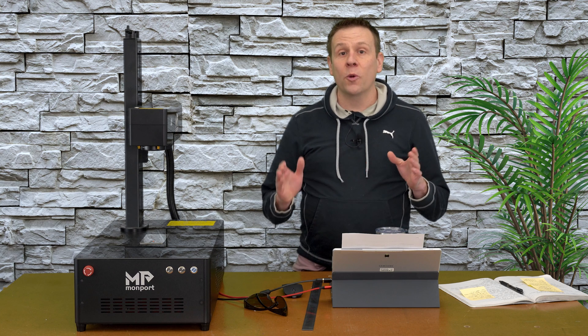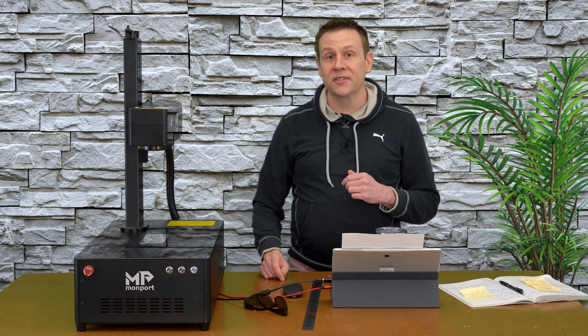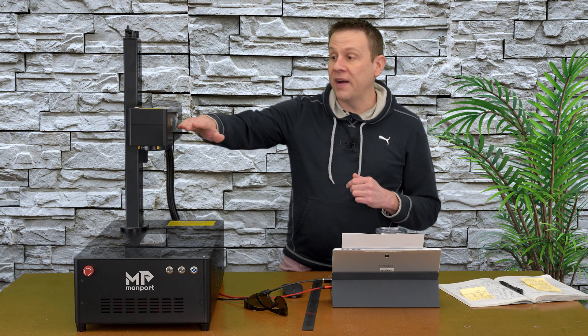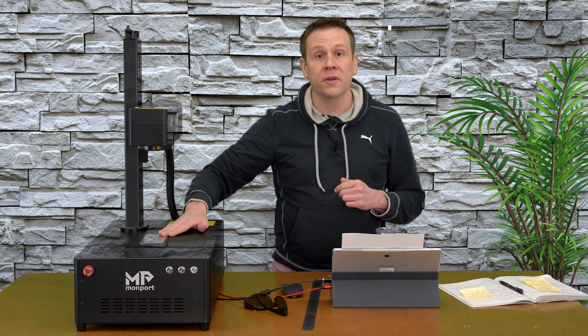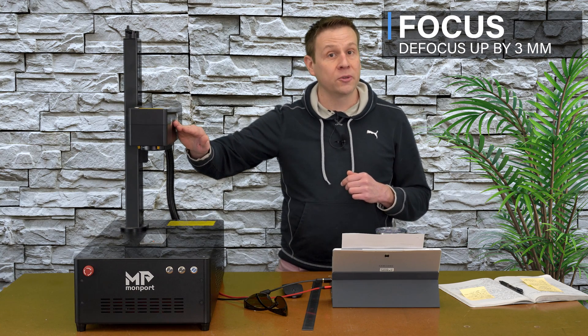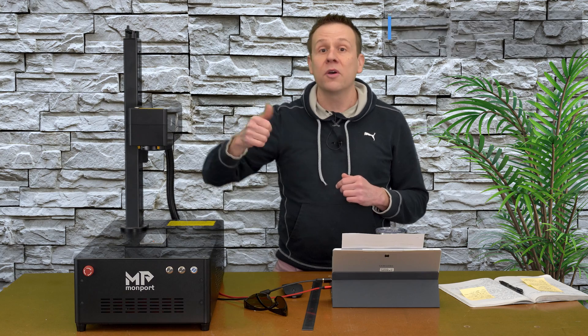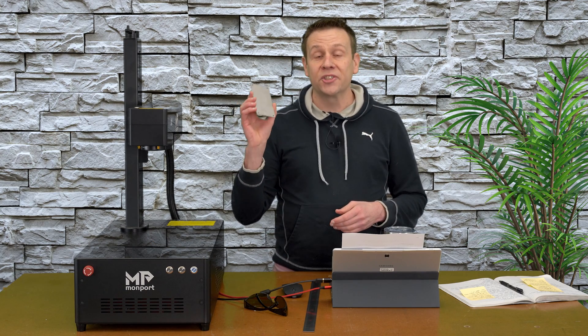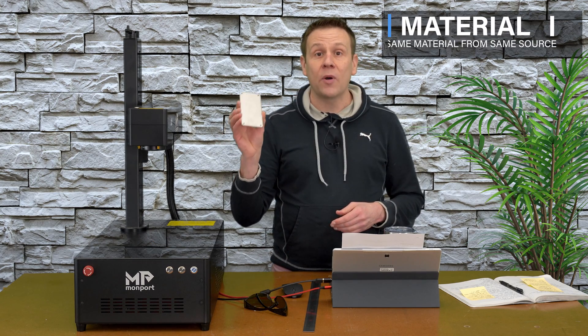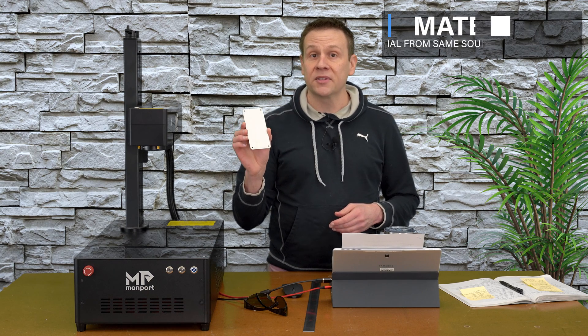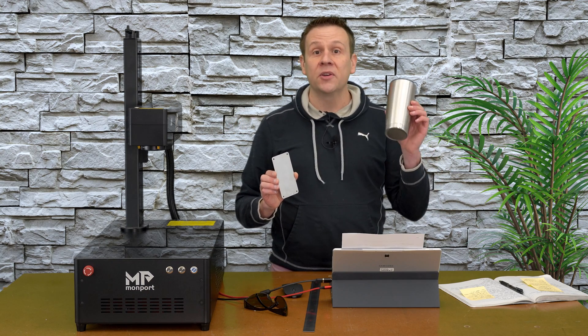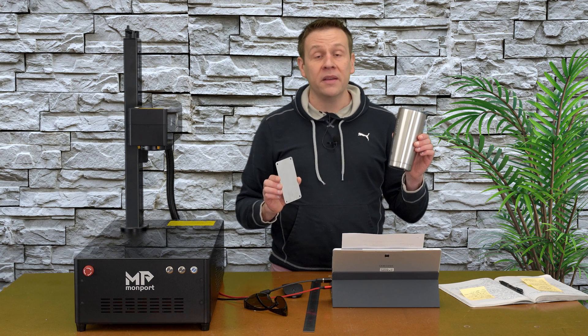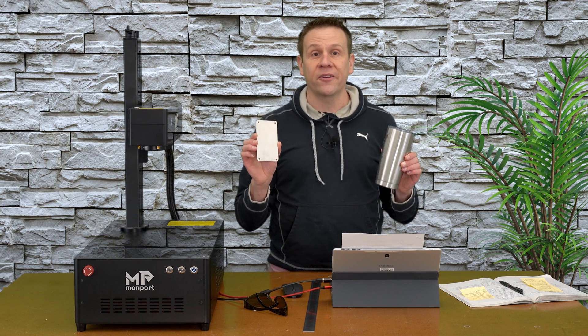Here's what we're going to look for when color marking that stainless steel. I'm going to be finding out the true focus of my laser machine down to the work material. I'm then going to defocus the laser machine head by moving it up 3 millimeters. The settings that I generate for the stainless steel, I want to make sure that I'm always using that same stainless steel. The settings that I'd use for a stainless steel tumbler will often be a little bit different than what I would use for this placard.